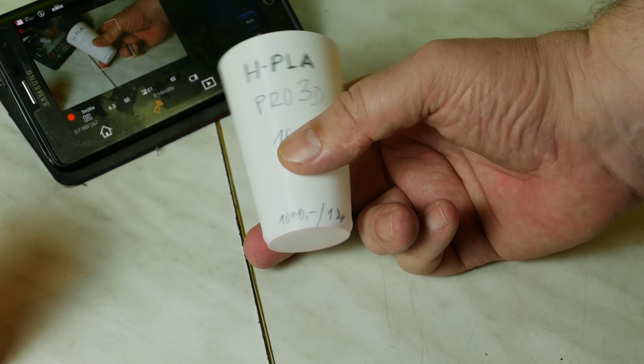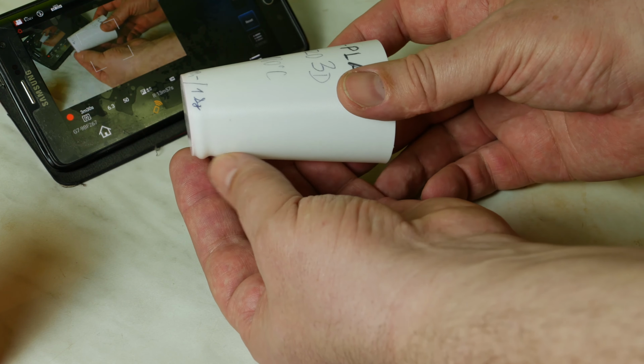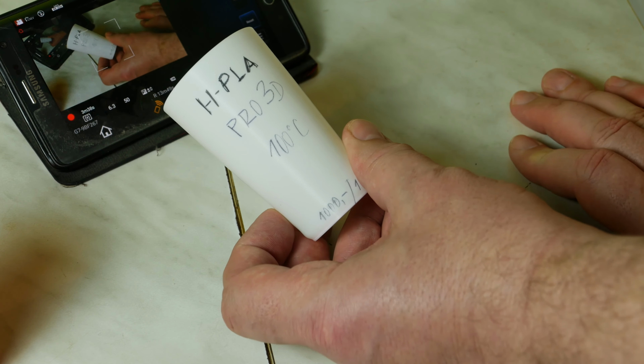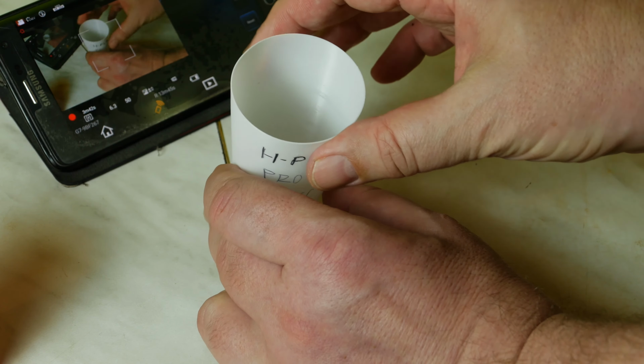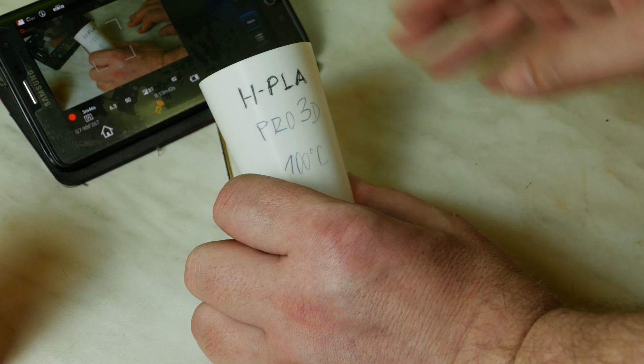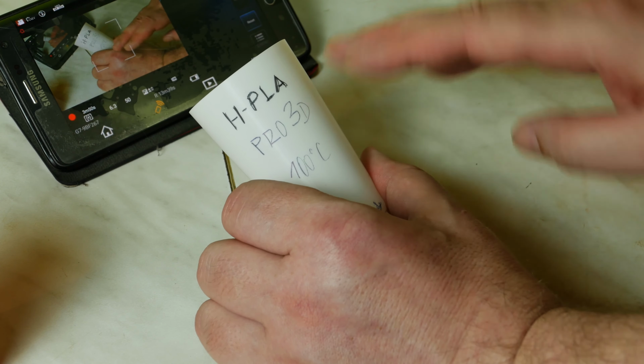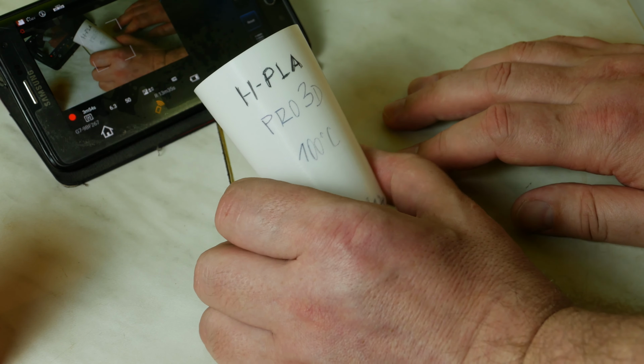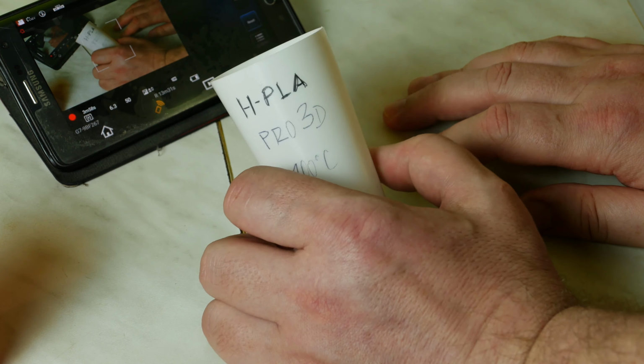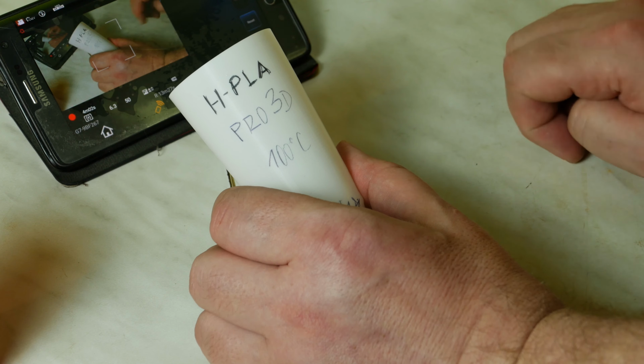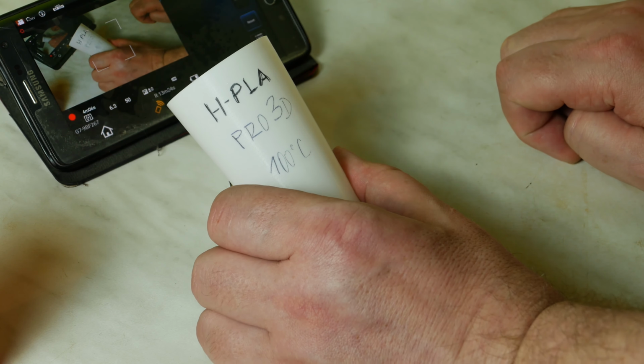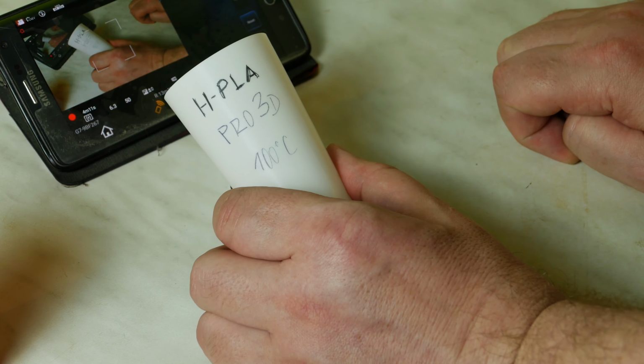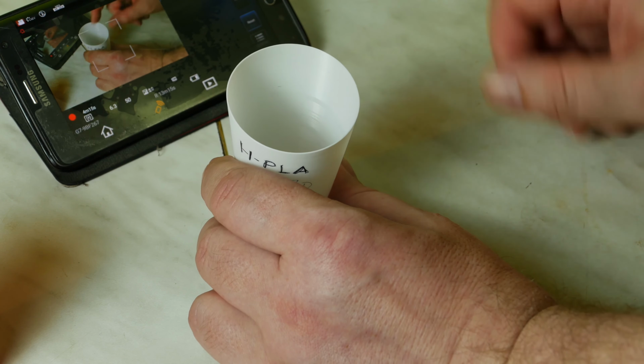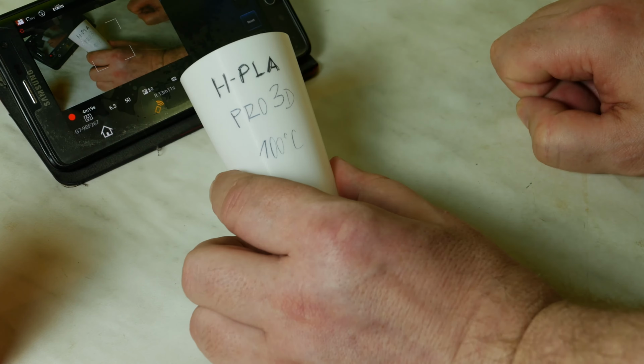Number 2, silver medal, HPLA. Why is this silver? Because you can see here some deformations. Yes, I see these deformations too, but this is only 100 degrees of Celsius resistance, and I think it is a good job for this material, because this material is really nice to print without any problems. Really nice for 3D print, and you can use it directly after print without any annealing process, etc, and you have 100 degrees. Okay, maybe not 100, maybe 80, 85. Yes, again it depends on thickness of walls, number of perimeters, infill, etc, but really good job.